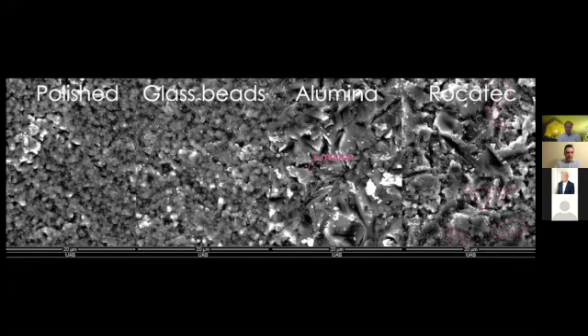The polished ones, the surface stayed pretty smooth. Glass beads don't really do anything to the surface of zirconia. They're not going to roughen it up at all. You can see here with the alumina particles, we've got these little divots in the zirconia that have actually created some roughness. And it's really easy to get that roughness on zirconia by sandblasting with alumina particles.